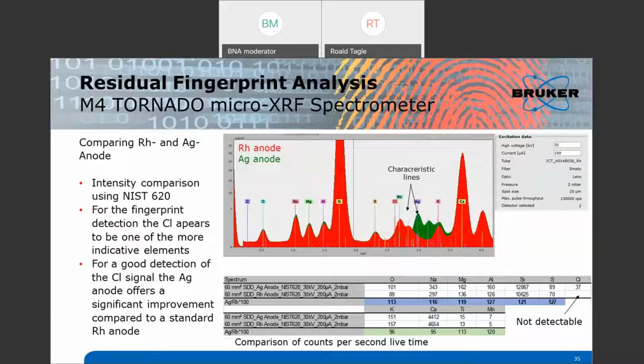But with a silver anode, we do see that there is a little chlorine peak, which we cannot detect with a rhodium instrument. If we have amounts of chlorine which are really detectable, we do detect it with a rhodium tube. We can deconvolve this, but in this qualitative approach, we have a much better contrast with the silver tubes. In principle, it doesn't mean that it's impossible to detect this chlorine, but in this case, you would need a filter to eliminate the primary radiation of the rhodium L line, and this would diminish a lot the sensitivity of the instrument for the chlorine.